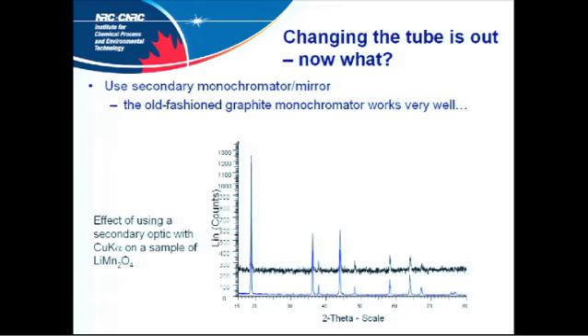If you can't change the tube, now what? It's old-fashioned, but it still works. The secondary monochromator does a pretty good job of stripping it out from the background. This is actually a secondary mirror, but it's pretty much the same thing. Here you get very noisy data, high background. With the fluorescence properly stripped out, that's a real peak in a spinel, and here you wouldn't be able to pick it up. You can compensate a little bit by counting for longer, but you still have issues with your peak to background, so it's not ideal. As I say, prevention tends to be better than cure.